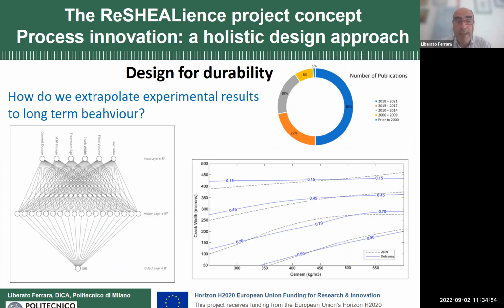Also, to extrapolate our experimental results to long-term behavior, we started to use artificial intelligence algorithms in the analysis of our data and of the literature data, because these materials, in some cases, are new. So you do not have statistics for the material strength or for other material properties, material performance indicators. So we use artificial intelligence algorithms to analyze our data in conjunction with the literature,